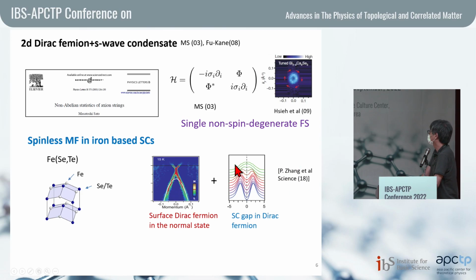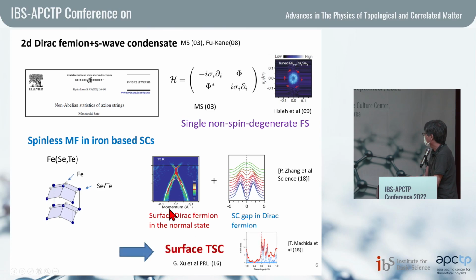And they also measured the gap at the Fermi level in the superconducting state, and this is the data. As you can see, at low temperature, this surface Dirac fermion shows the superconducting gap. So this means that we can obtain the surface Dirac fermion with the superconducting gap. So from our Fermi surface criterion, we can expect topological superconductivity. And actually, they predicted surface topological superconductivity in the system. And as I mentioned before, this STM data is very consistent with the presence of the Majorana zero mode in the vortex. So in this case, we can confirm the correctness of our Fermi surface criterion.